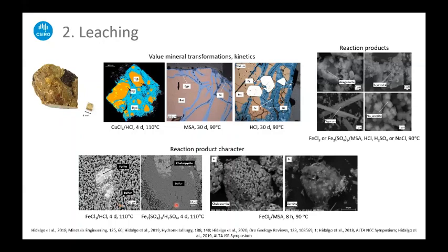And then interestingly, if you look at, for example, the chalcopyrite and the bornite, the sulfur layer that forms at the surface, the morphology is quite different. So you get a more amorphous type morphology in the case of the bornite. And all this fundamental understanding is important to understand what leaching reactions the minerals undergo, what products are formed, what speed minerals are leached at, what reaction products are formed that could be generating precipitates and resulting in blockages, etc.